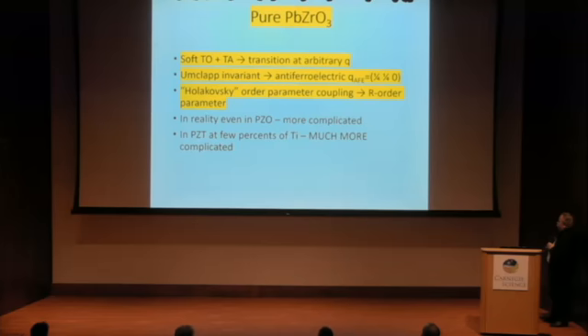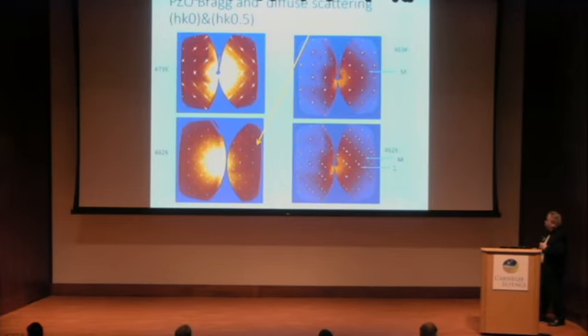an explanation that looks consistent. Soft TO mode plus TA transition at arbitrary Q, then Lifshitz invariant, anti-ferroelectric at exactly 1/4. Then Holakovsky order parameter coupling to the R order parameter. But in reality, even in the pure lead zirconate the situation is more complicated, I'll show you. And in PZT, at a few percent, or even less than 1% of titanium, there is a much more complicated structure pattern. So this is pure lead zirconate.